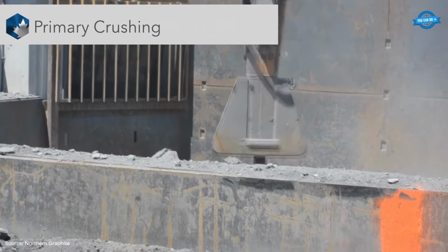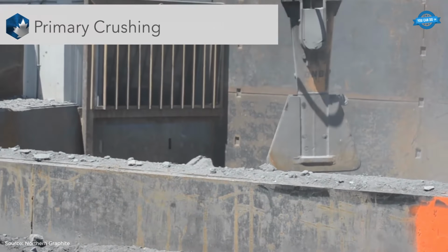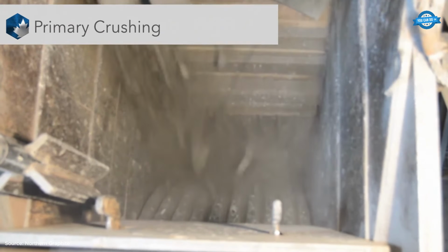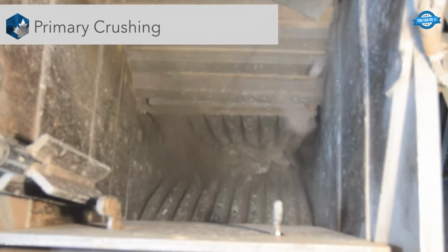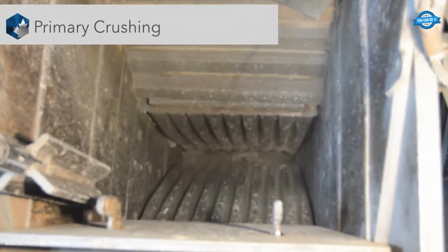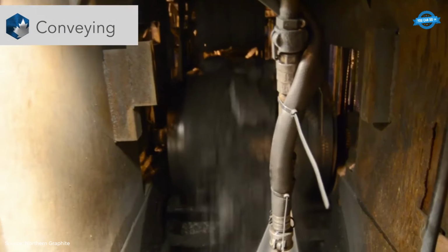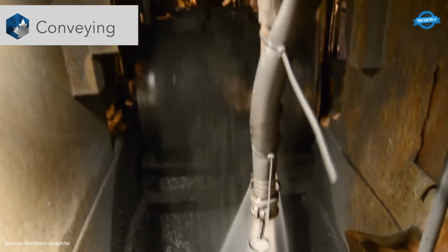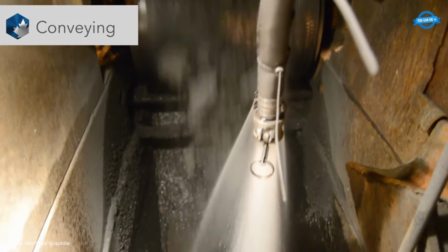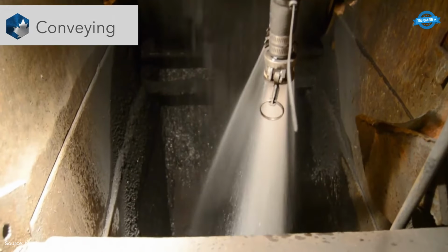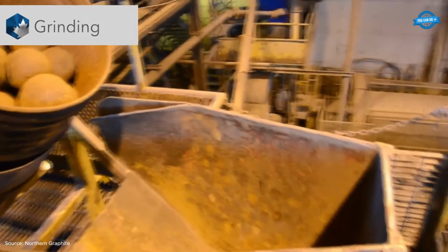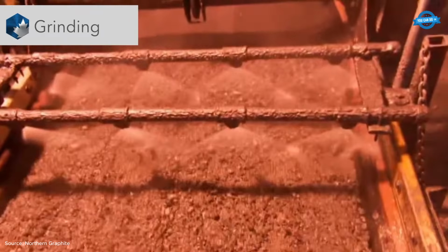During grinding, the ore is mixed with water in ball mills, producing a slurry in which graphite flakes begin to separate from the gangue. This slurry then enters the flotation circuit, the heart of graphite processing. Here, collectors and frothers are added in carefully measured drops to enhance the hydrophobicity of graphite particles. As air is introduced, graphite attaches to the bubbles and rises to the surface as a concentrated froth, while waste minerals sink.